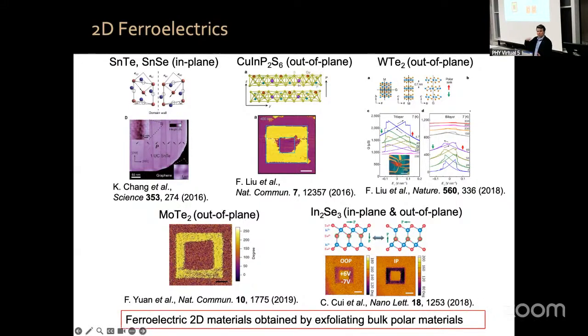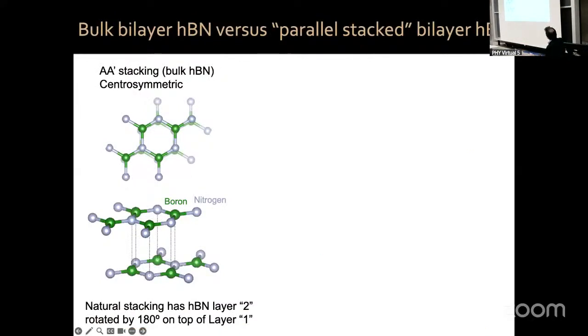These are all materials which are strong ferroelectrics that still survive when made very thin, because they're very strong or because of some particular accident. What I'm going to tell you about is making a ferroelectric out of a non-ferroelectric component—in the same way we made a superconductor out of a non-superconducting component, since graphene is not a superconductor. For that we can use bilayer boron nitride. Boron nitride has alternating boron and nitrogen atoms. The usual stacking when you grow a crystal of boron nitride is this AA-prime stacking, where boron and nitrogen atoms alternate in the z direction, exactly on top of each other. That also means layer number 2 of bilayer boron nitride is rotated 180 degrees on top of layer number 1—that's how crystals naturally grow.